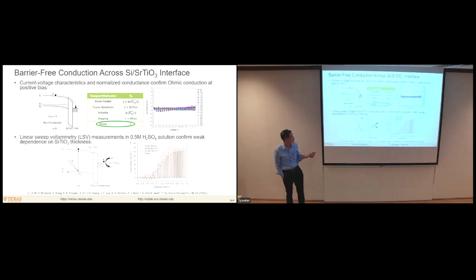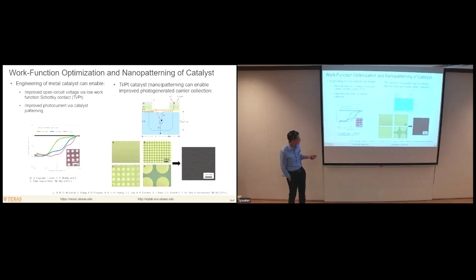So we made a bunch of these structures. We were able to show that, in fact, one does have very good conduction of electrons across this layer. And also, if you make photoelectrodes, photocathodes in this case, right, which are performing the hydrogen evolution reaction, then there is very little dependence of the performance of these structures on the thickness of the strontium titanate, which is what you would expect if you have this kind of picture over here. If what was really happening was tunneling, then the current would decrease exponentially with increases in the thickness, and that's not what we observed. So we went ahead with this.